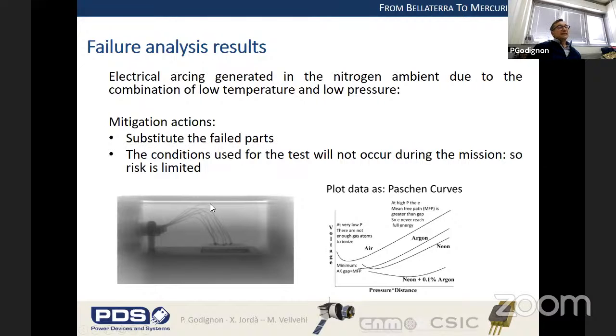So why didn't we detect that in our standard test? Because we perform this isolation test at room temperature and at atmospheric pressure. But when you decrease the temperature and you decrease the pressure, the minimum distance needed for having an arcing between two electrodes is increasing. So you can have an arcing under these low temperature and low pressure conditions that you will not observe in, let's say, the standard atmospheric and room temperature conditions.